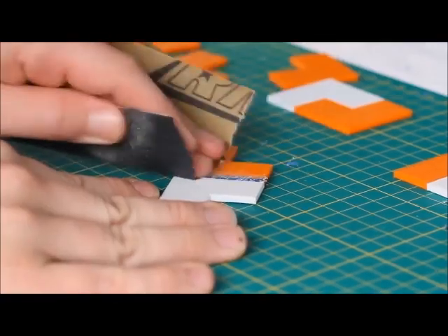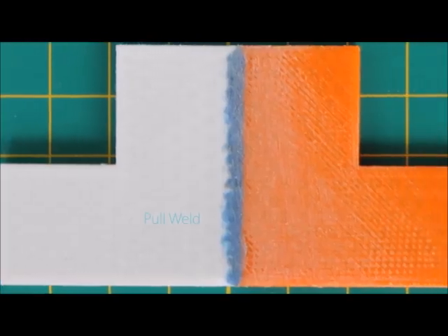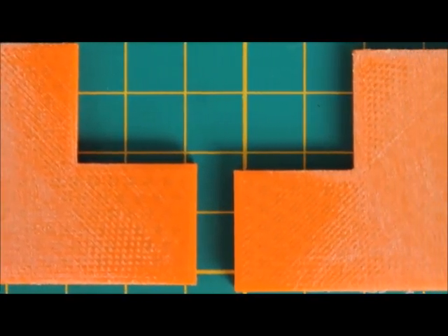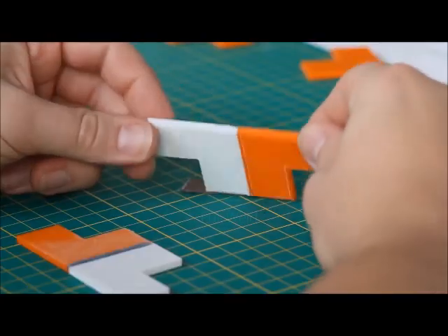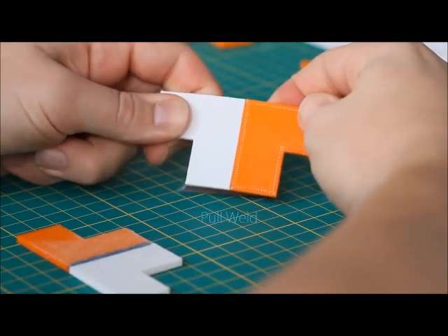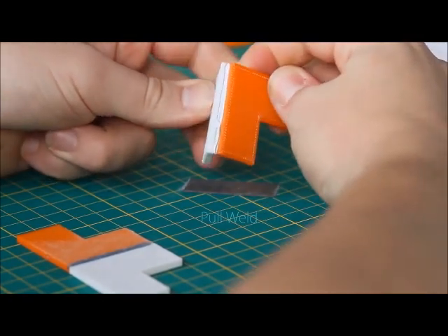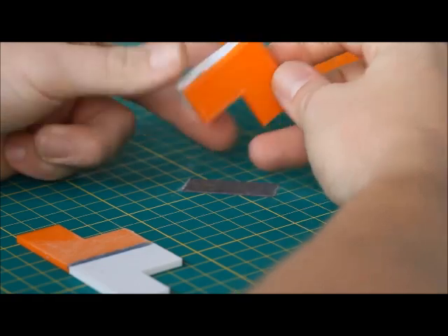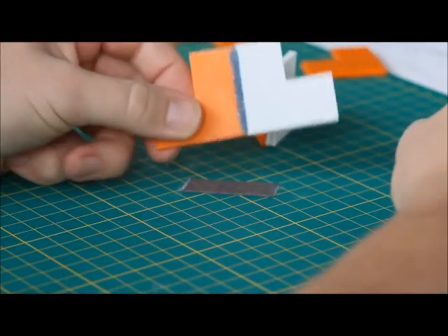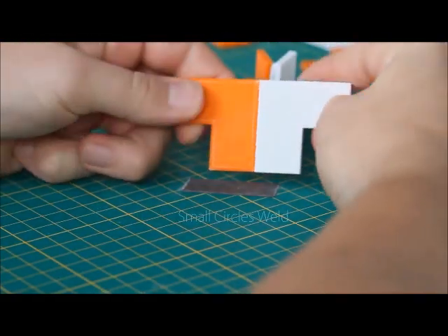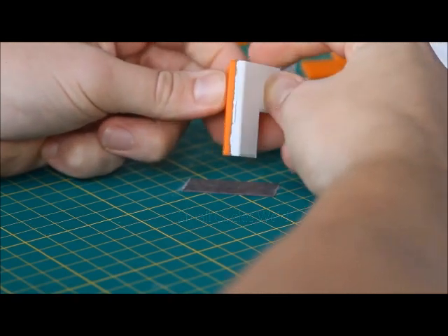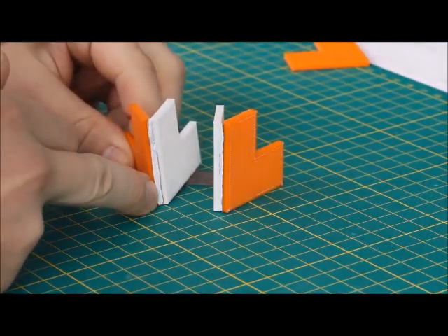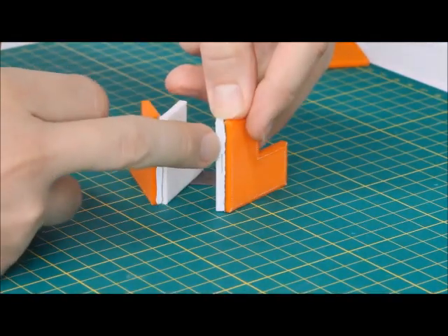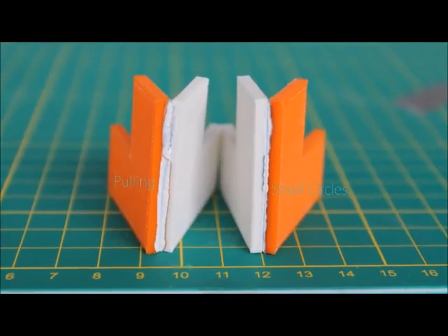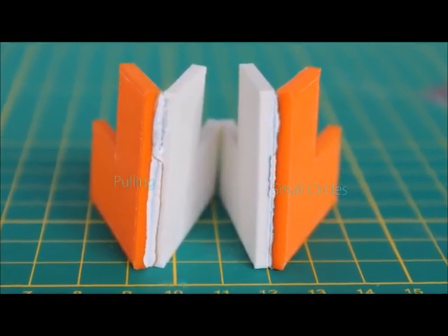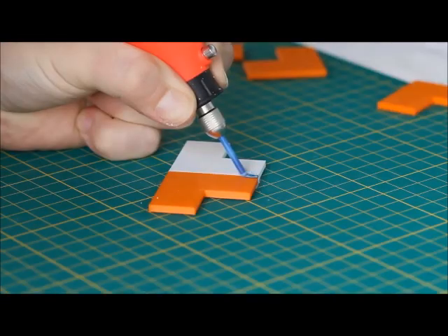Now let's compare the two welding styles. Once both welds are ground back to a flat surface, we can break the welds to check the penetration depth. This first weld is the pulling technique. This is a really strong weld, and you can see the weld has penetrated down through the layers, fusing the two parts together. The small circles, on the other hand, is much weaker and has only penetrated the first 5 to 10 layers. So where the small circles is better on the surface, if you need strength, use the pulling technique.